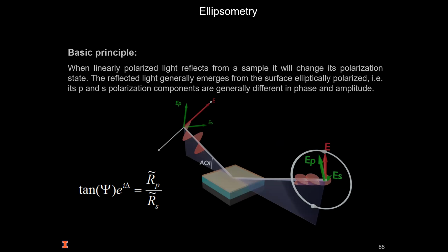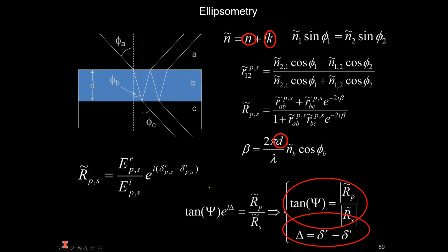In ellipsometry, we commonly measure the ratio between the components polarized parallel and perpendicular to the plane of incidence of a linearly polarized light beam reflected from our sample, and the phase difference between them as well. From these values, which we commonly express in terms of ellipsometric angles psi and delta, we can determine, for example, the thickness of the film and its dielectric function or complex refractive index by fitting the experimental data to a physical model of our sample.